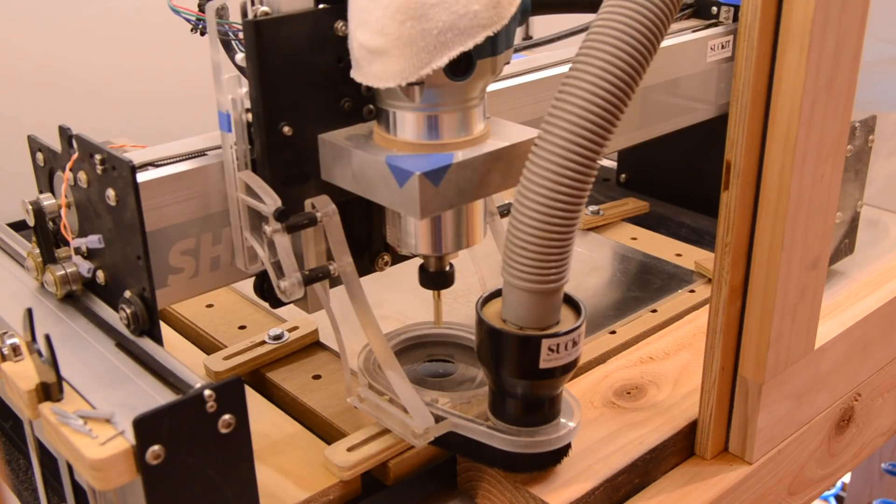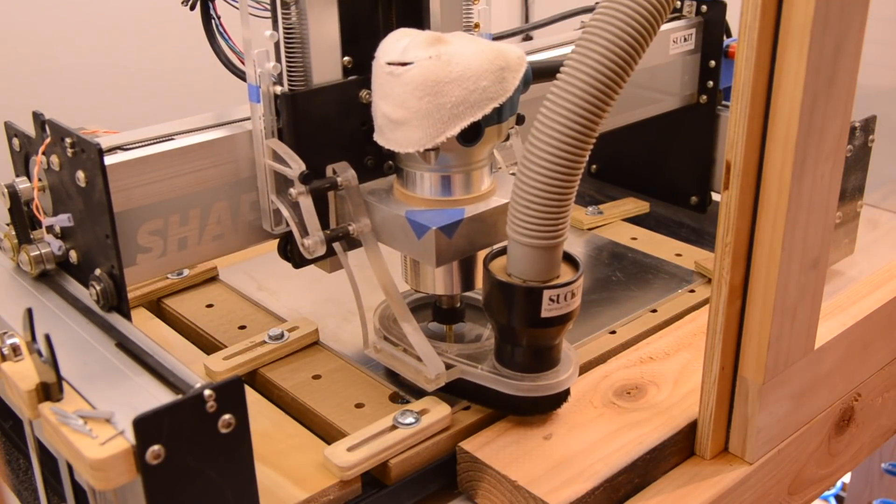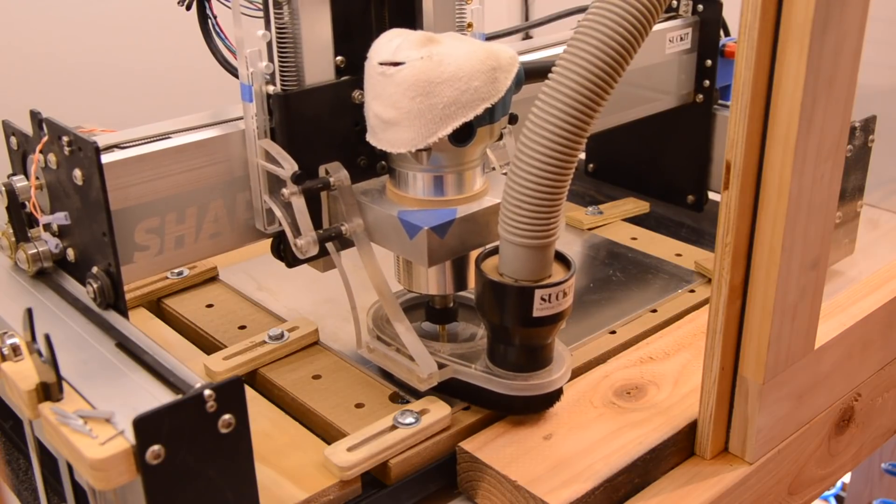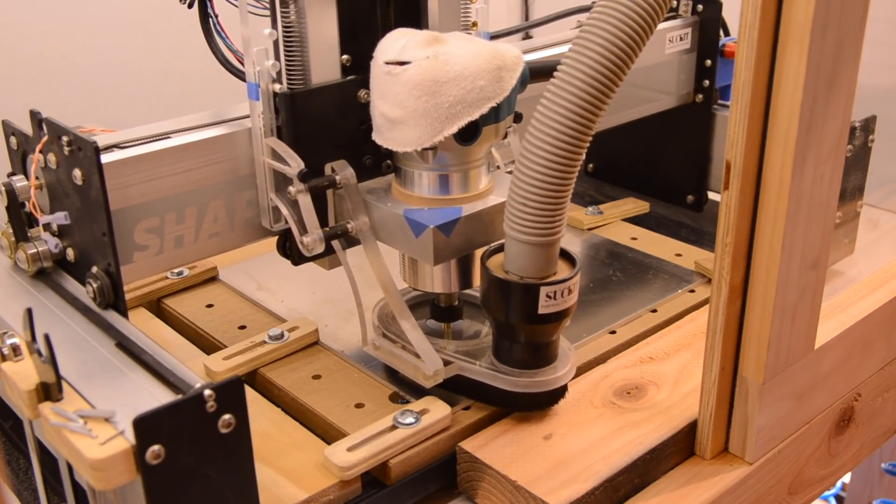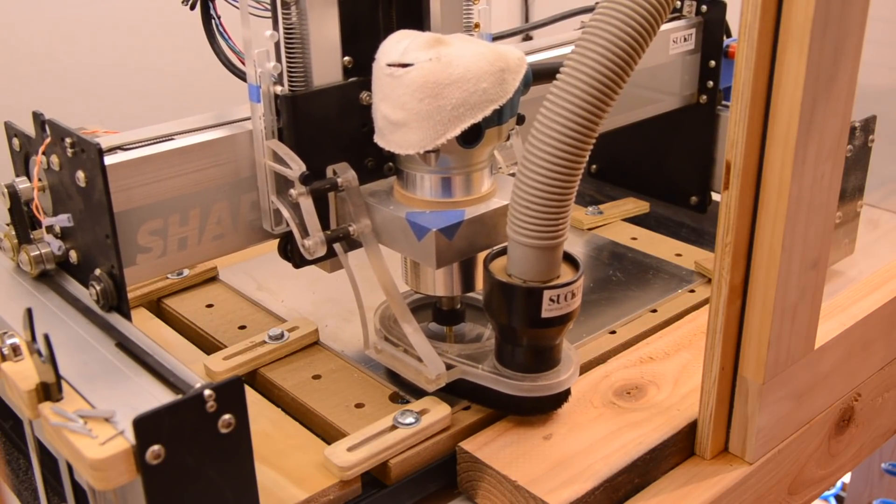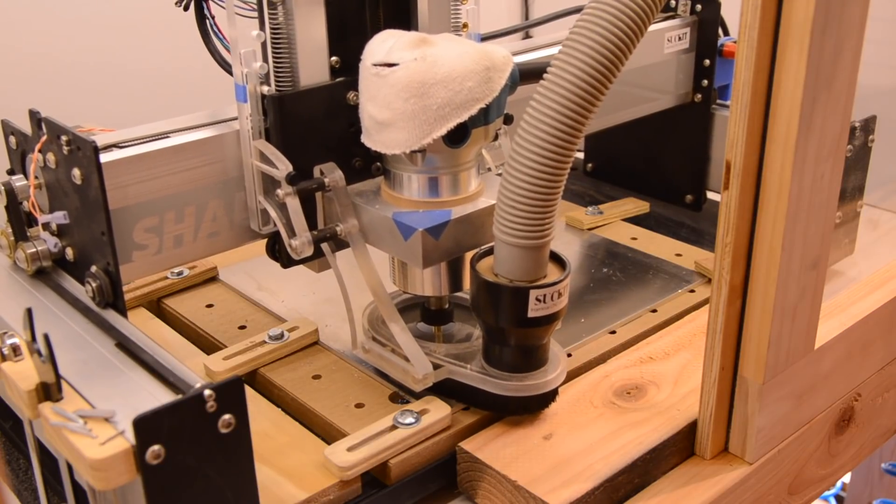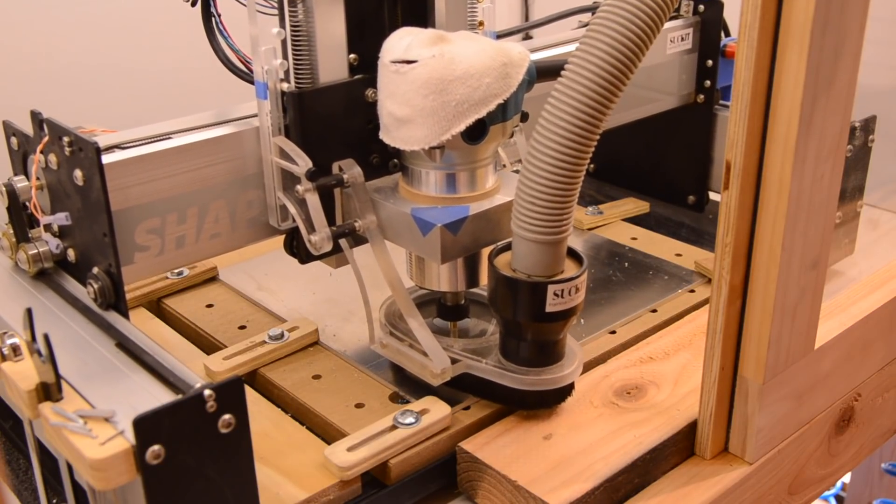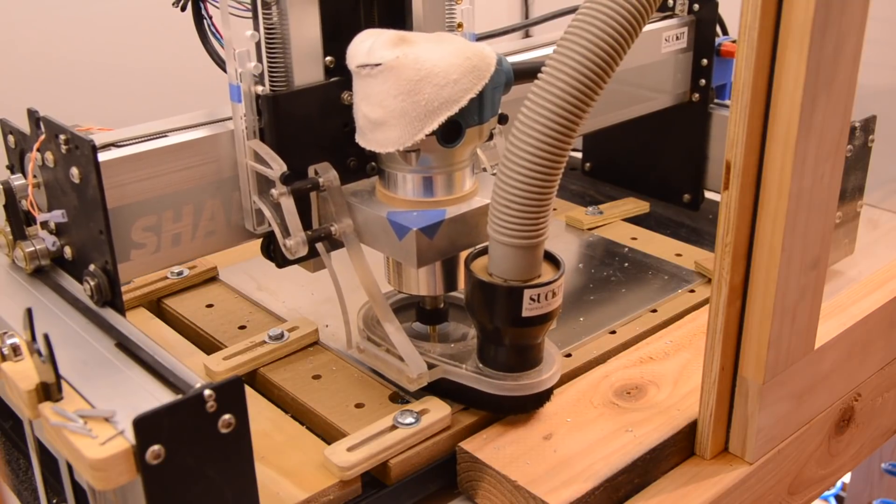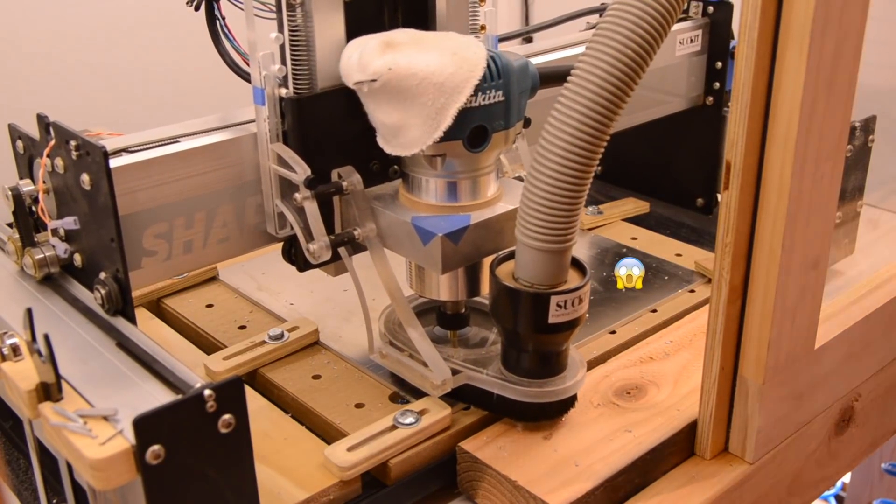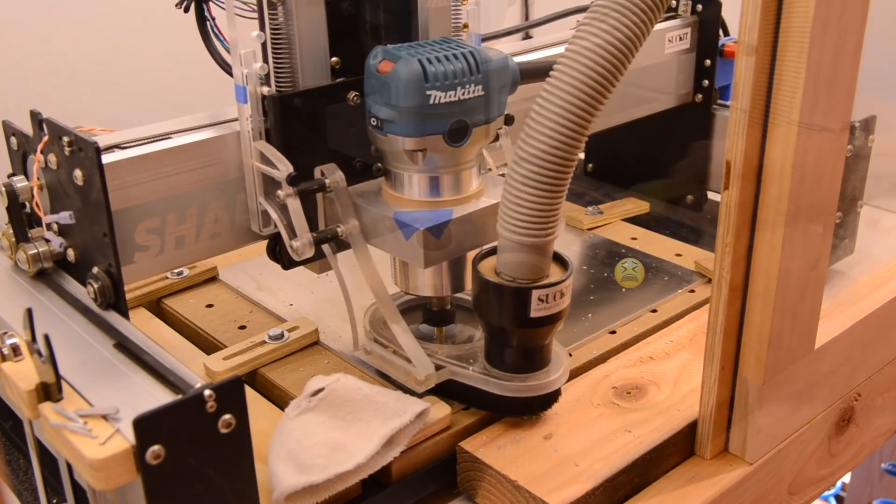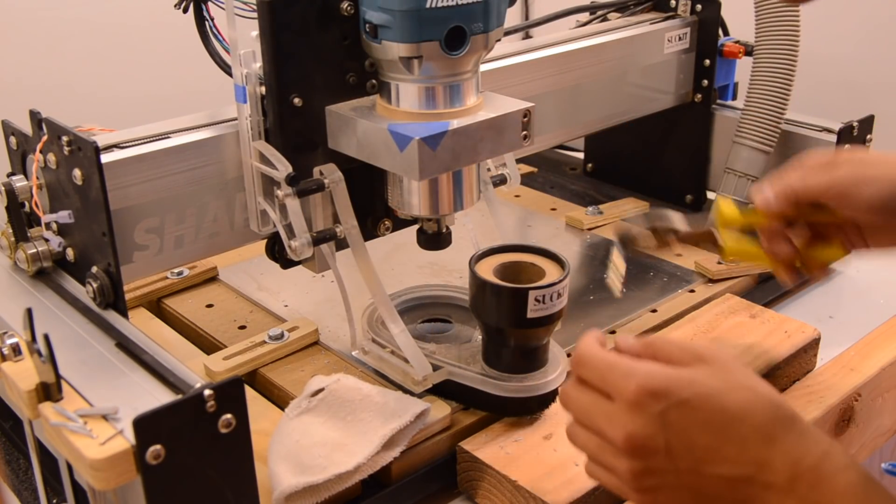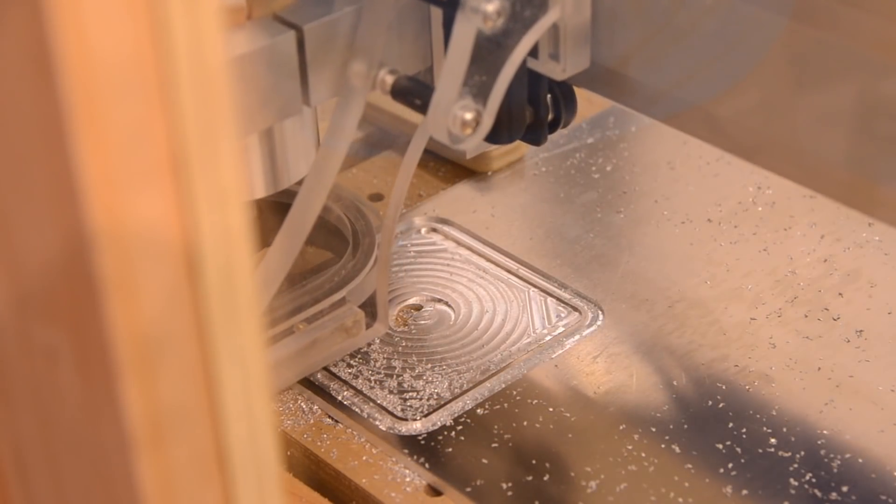Once I got home, I dropped a plate onto my machine and held it down with a combination of clamps and double-sided tape. I loaded up a quarter inch zirconium nitride coated end mill, generated some experimental toolpaths, and said a quick prayer to the machining gods. But what I should have done instead was checked my collet tightness. I'm used to cutting wood, where you can sufficiently clamp down on your end mill just by using the spindle lock and a single wrench. But end mill torques when you're cutting aluminum are way higher, and I destroyed my first test piece. Fortunately, I didn't destroy my end mill.